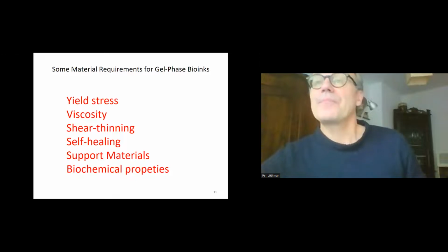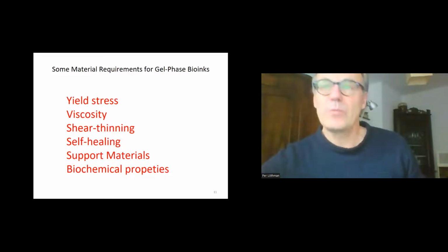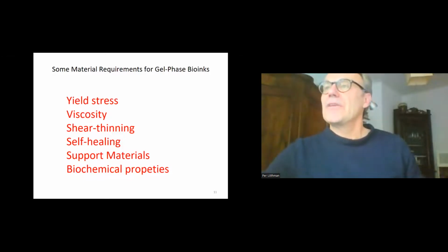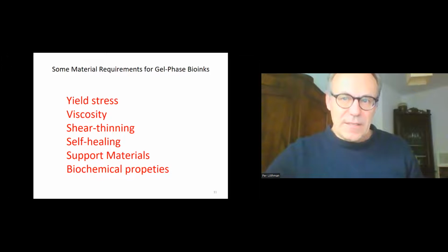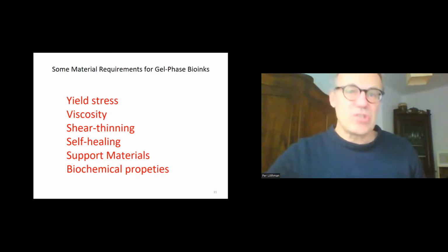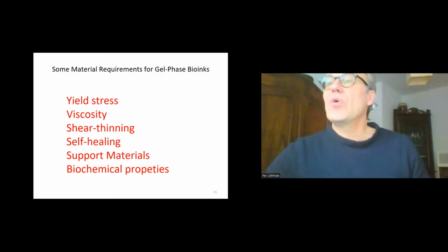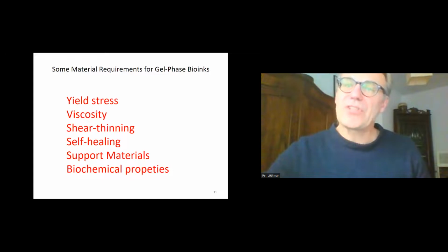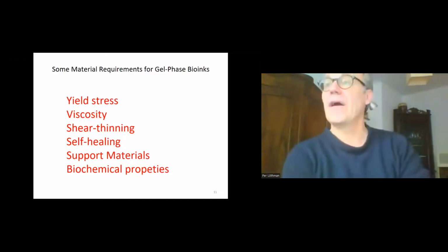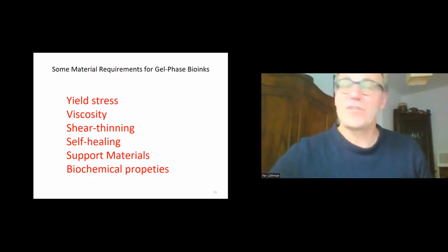The viscosity is a measure of the resistance to flow. That's a general statement, and we know that. So it influences the bioink's ability to be extruded, and it plays a role in print fidelity. Higher viscosity impedes droplet formation, which is important. We need to print with a continuous filament since the printing itself is layer by layer. So high viscosity inks are preferred, also in terms of resolution and shape retention after printing. However, if the viscosity is too high, the print needle might be resistant to flow, leading to an inconsistent deposition. So there is a balance here.